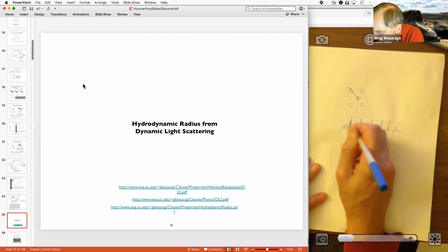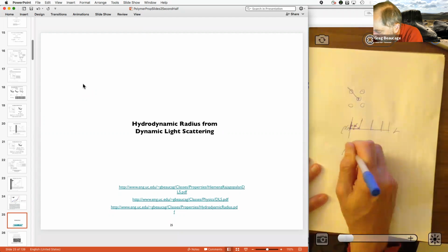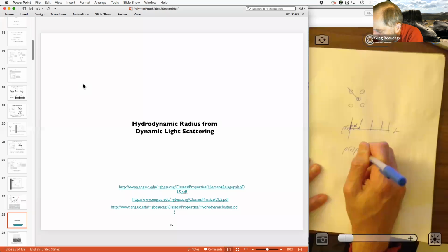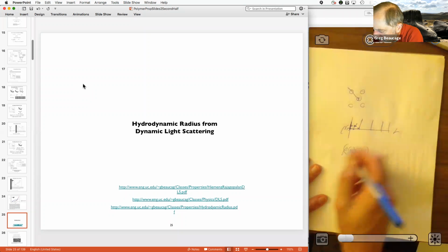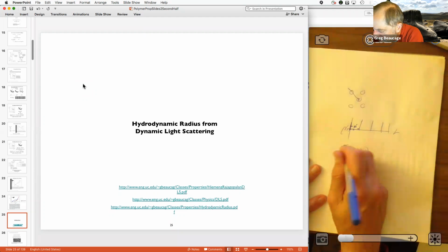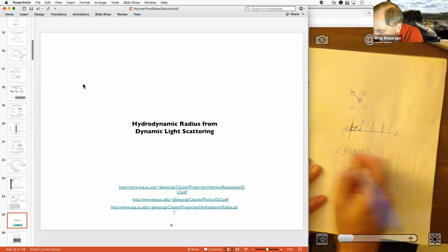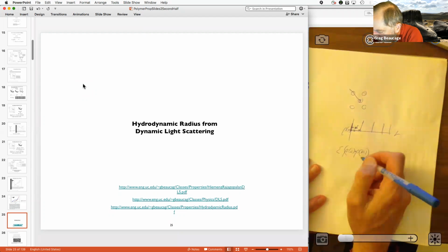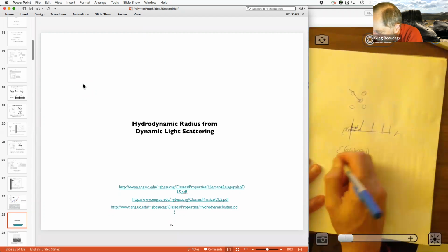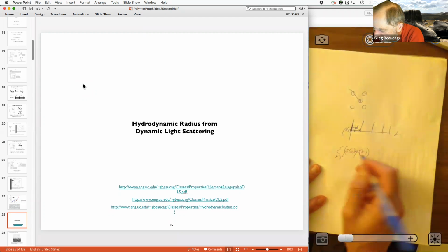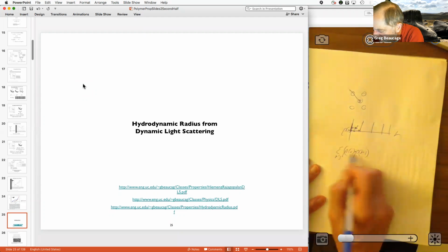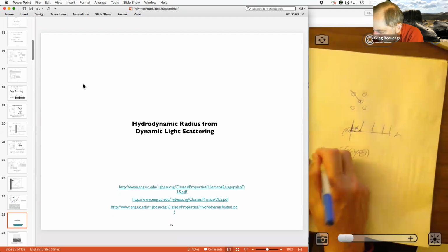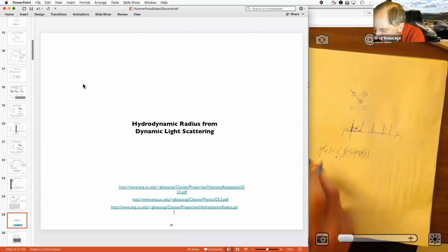So I take this point times that point. I take the density at 0 and the density at r, and multiply the two together. Then I can sum those up, as long as I sum over all starting points. That's a correlation function. So it's like the density at 2 points separated by distance r is going to be this g of r, this binary correlation function.